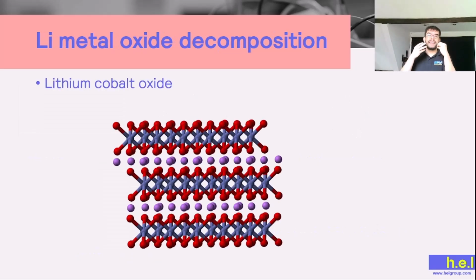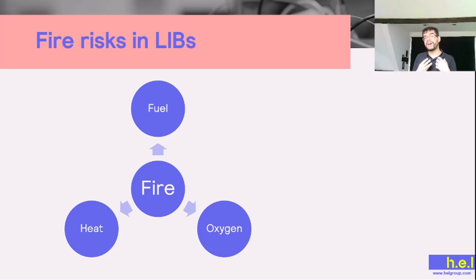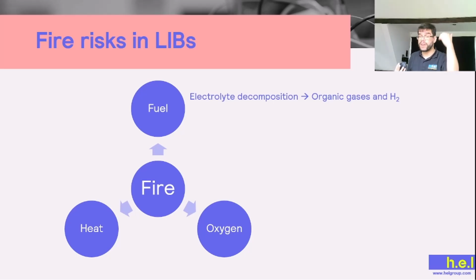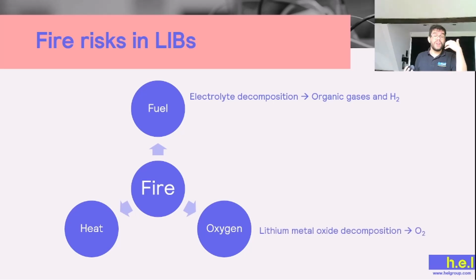But also the lithium metal oxide can decompose. In this case, metal oxides such as cobalt oxides can decompose, generating cobalt metal and oxygen. And this links very much with fire risks. If we remember the three things that we need for a fire or an explosion to start, we need a fuel, which in this case is provided by the decomposition of the electrolyte, with things such as organic gases and hydrogen. We need oxygen, and the oxygen is provided by the lithium metal oxide decomposition. And finally, we need heat, and the heat is going to come from thermal runaway reactions. So we have the three ingredients for a fire, making the situation quite risky.